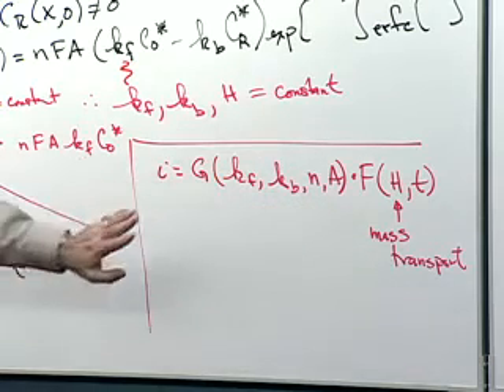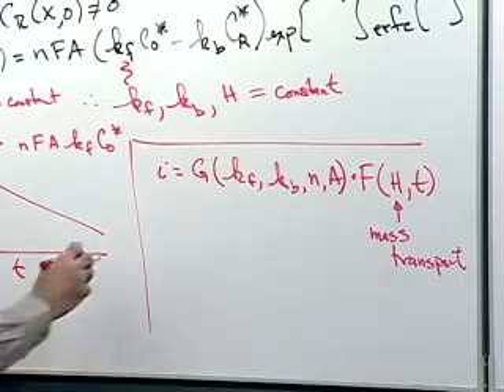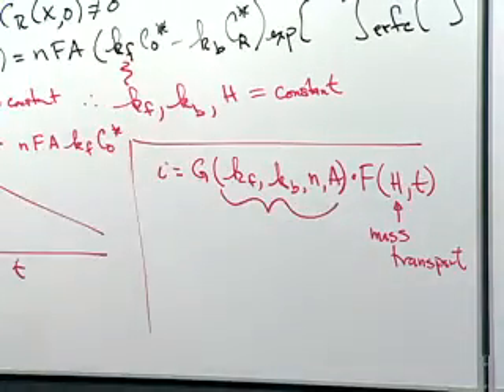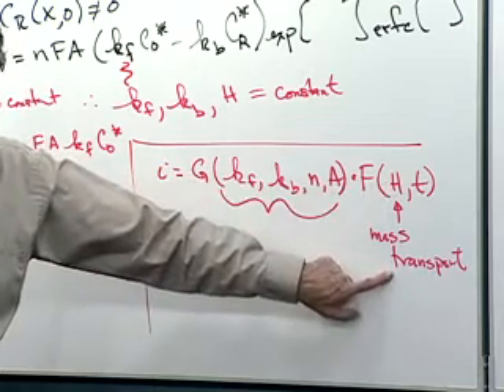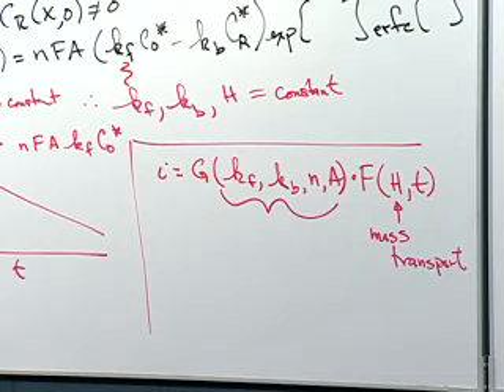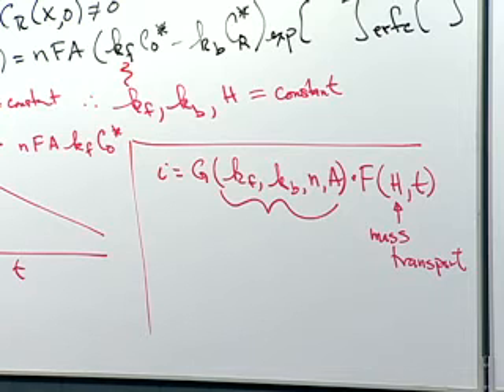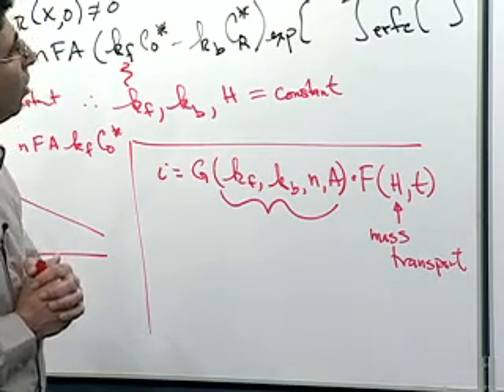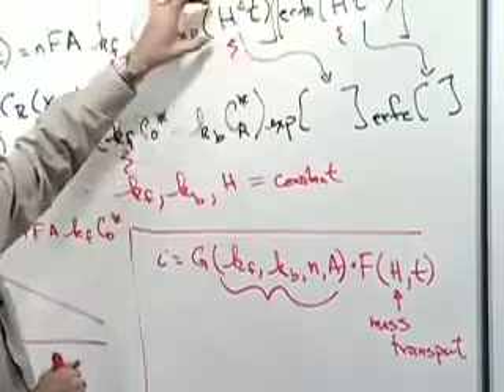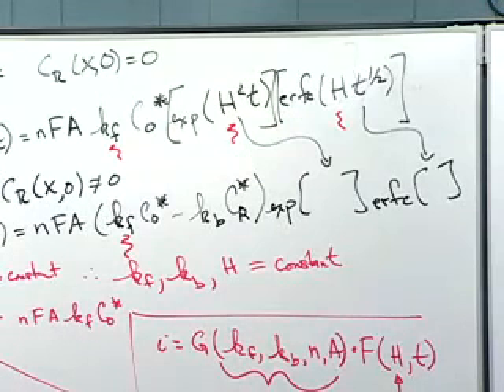Okay, now, did I just do something that was fair? You'd probably all agree on the charge transfer parameters here, things like the rate constants, the number of electrons. That all sounds fair for charge transfer. But is it fair to include H as a mass transport sort of phenomena? After all, look at H. It has diffusion coefficients in it. That certainly has to do with the transport of material, but it also has rate constants in it. Well, one way of answering this is saying, well, if you look how you're going to do the experiment, you sort of finesse it in that if we're looking at short times, then we can always make these numbers as small as we need to by adjusting the time scale we're on, since we're multiplying by H. That really doesn't, though, totally answer the question I'm getting at.